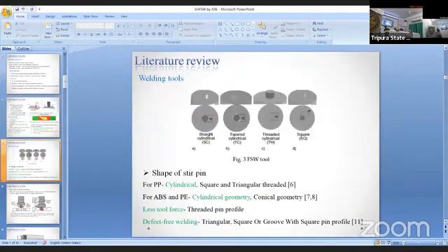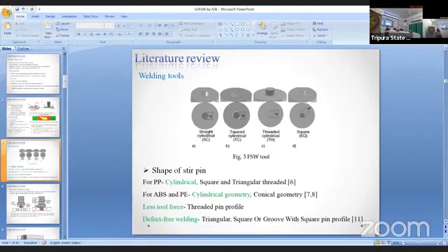Now, as we have said, the shape of the welding tool also plays an important role in the quality of welding, especially the shape of the stir pin. It has been seen that for polypropylene, cylindrical, square, and triangular headed threaded tools have been successful. For ABS and polyethylene, cylindrical geometry, conical geometry, and whenever we use threaded pin profile, then less tool force is required, and with the help of triangular, square, or groove with square pin profile, defect-free welding could be achieved.